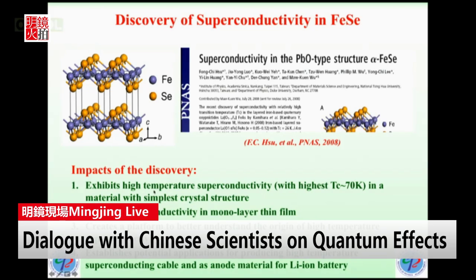And it can have a relatively high TC also. Over the past 10 years, we found it can have close to 70K transition temperature. And you can even make it into just a single layer and it is still superconducting. This is very, very intriguing. And so we have created a platform to better understand the origin, because a simple structure should always let us learn more. And it's interesting that it can have very important applications also, okay.